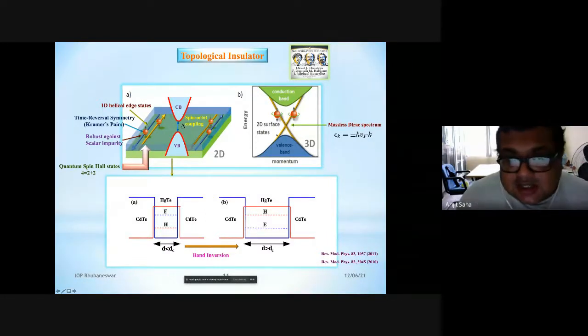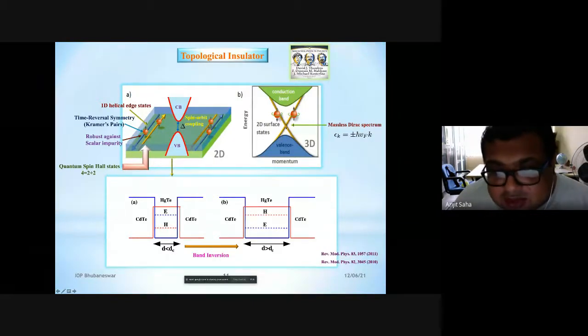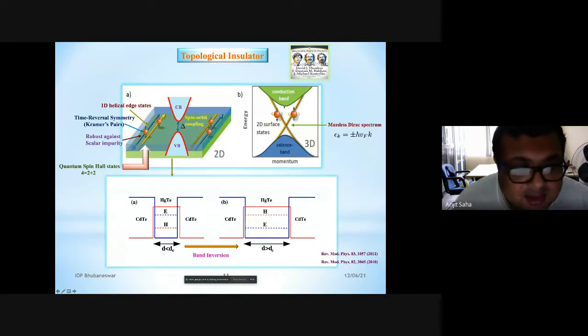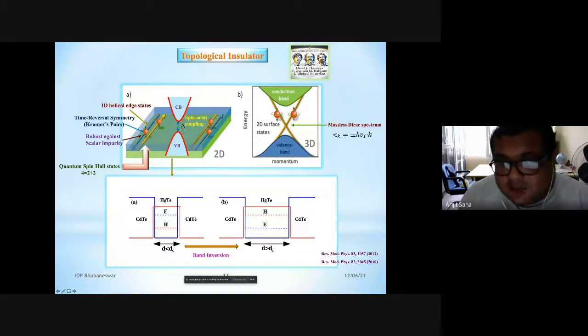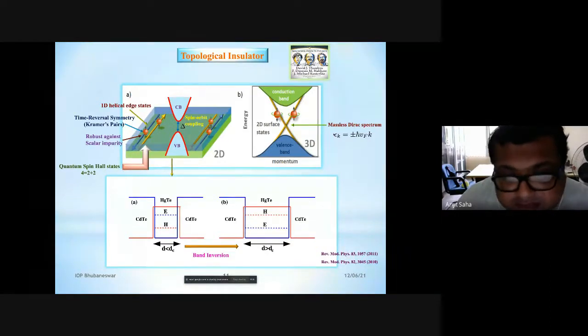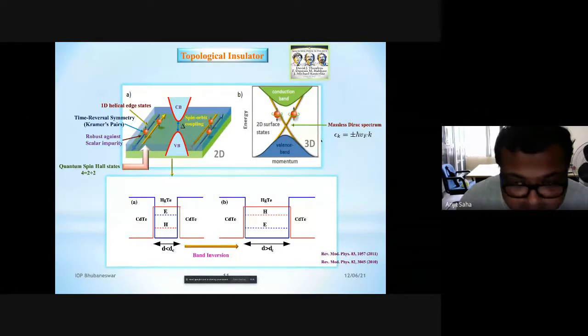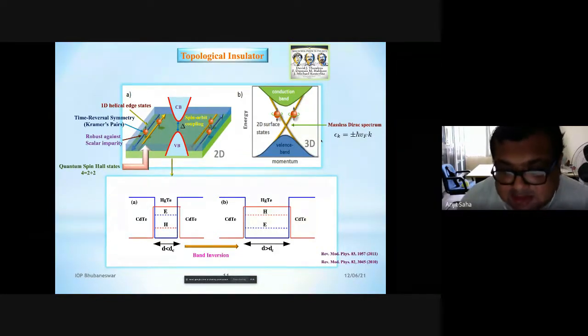So this is the 2D picture. If you generalize to 3D, then in 3D the boundary is the surface. So you get surface modes as metallic surfaces for a 3D topological insulator. And the interesting thing is that this 2D surface of a 3D topological insulator satisfies a massless Dirac spectrum, which I have shown before. So they follow a massless Dirac spectrum in 2D when they are in the 2D surface states. But the bulk of this 3D topological insulator is completely gapped, behaving like a band insulator. And also on the surface of this 3D system, the momentum and spin of the electron are coupled. So there is spin momentum locking.